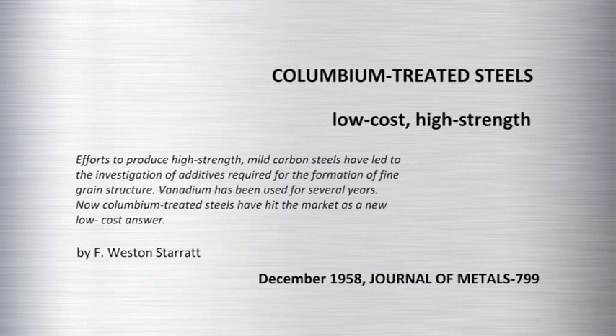And it was amazing because this was a microalloying addition of niobium, and of the order of 0.01% niobium gave a 25% increase in steel strength. So it created a sensation worldwide. At that time in the 1950s, niobium was used as an addition to fairly exotic stainless steels, particularly creep-resistant stainless steels. It was also used as an addition to superalloys, which were used, for example, for gas turbines. But it was not used as an addition to ordinary carbon manganese steels.